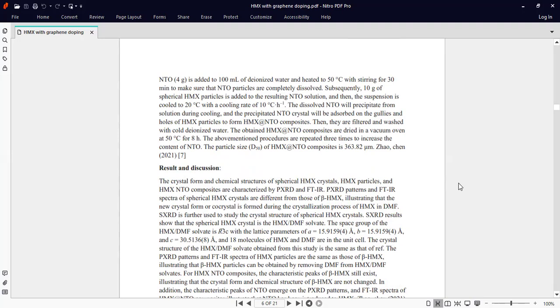The dissolved NTO will precipitate from solution during cooling and the precipitated NTO crystal will be absorbed on the gullies and holes of HMX particles to form HMX NTO composites. Then they are filtered and washed with cold deionized water. The obtained HMX NTO composites are dried in a vacuum oven at 50 degrees Celsius for 8 hours. The above mentioned procedures are repeated 3 times to increase the content of NTO. The particle size of HMX NTO composites is 363.82 micrometer.